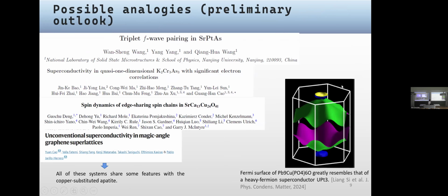So there are listed several systems that share some analogies and similarities to the doped apatite systems. The first one, basically the similarity is the hexagonal symmetry and strong Coulomb repulsion, the strongly correlated regime. The other one is quasi-one-dimensional while also having a hexagonal structure. Same as the next one. This is bilayer graphene, also similar in terms of band structure, the correlation regime and crystal symmetry. And this paper already pointed out an almost visually exact correspondence between the Fermi surfaces of the copper-lead apatite system and uranium platinum 3, which is a heavy fermion superconductor.